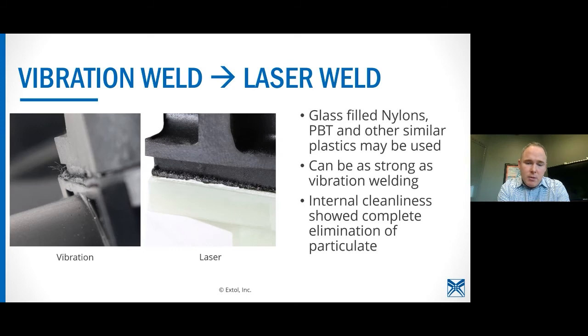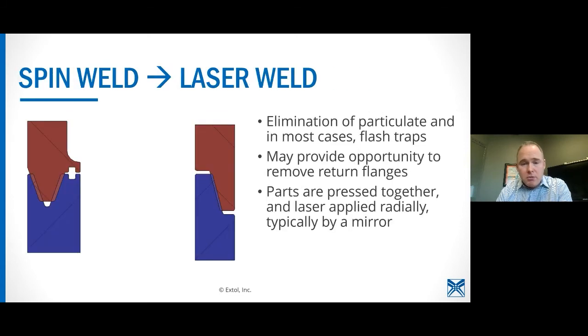We saw in a case study where internal cleanliness showed a complete elimination of particulate, where that particular application was an underhood component, and it had unacceptable internal particulate. So definitely feasible. In this particular case study, we proved feasibility and cleanliness without any design changes. So just keep that in mind. Typically, we see that we need 2.5 millimeters or so of transmissive thickness. So if you've got that sort of application, we'd love to take a look and see if it's feasible. You may not need changes to your part. In some cases, there are changes required, but we definitely can identify those in our applications lab.